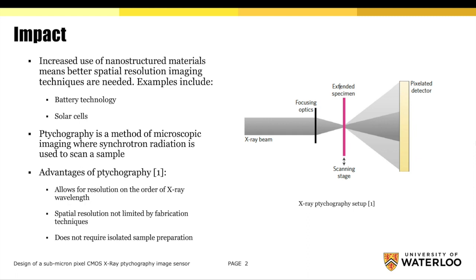X-ray ptychography can be used to achieve this nanoscale characterization. Ptychography is an imaging technique in which a focused coherent x-ray beam, generated by synchrotron radiation, is used to scan a sample. Ptychography has multiple advantages over conventional x-ray imaging techniques, the main one being that it allows for wavelength-limited resolution.